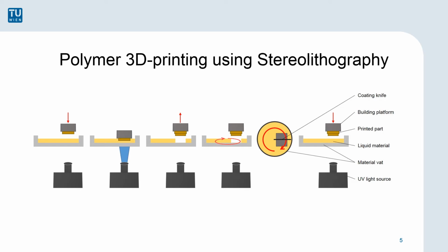With that, I would like to come to the third term, which is 3D printing. 3D printing is based on the principle of the production of samples in a layer-wise process. In our case, the raw materials are photopolymers based on acrylates and methacrylates. In combination with the photoinitiator, these liquid substances form polymer chains and solidify by radical chain polymerization when exposed to a suited light source. The principle of radical chain polymerization is used in a stereolithographic or SLA process.